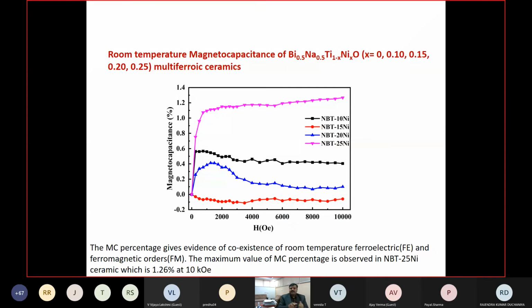So what important he did in this case, he measured the magnetocapacitance. Magnetocapacitance means he observed the capacitance with the applied magnetic field. And he observed the maximum magnetocapacitance in the case of 25% nickel doped. For 10%, it is in between. For 15 and 20%, it is not showing good behavior. So again, we have to optimize which composition is good. So magnetocapacitance is showing the multiferroic behavior. Multiferroic means ferromagnetic as well as ferroelectric. Both ferroic orders are coexisting in these types of compositions.